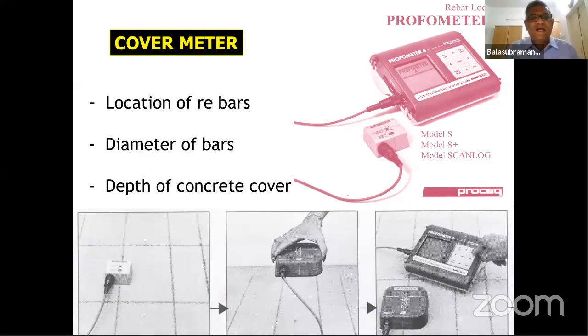And it can predict the diameter of the rebar, but there can be an error of plus or minus 25% in the prediction. Hilti also has a much better equipment. This profoscope is about 5 lakhs. That one is about, I think, 15 to 20 lakhs. There they say it can be one diameter more or one diameter less. So prediction of the diameter of the rebar is a little dicey.